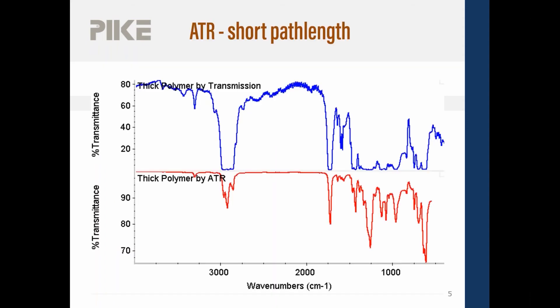So here's an example of a thick polymer run in transmission and by ATR. Let me grab my little bouncy ball. Okay, so because in transmission, it's a thick polymer, we're just saturating through here. However, with ATR, because it's a surface technique, now we can resolve these bands.